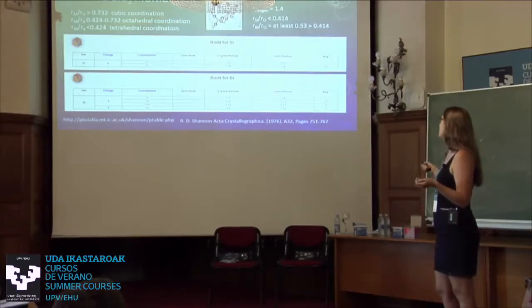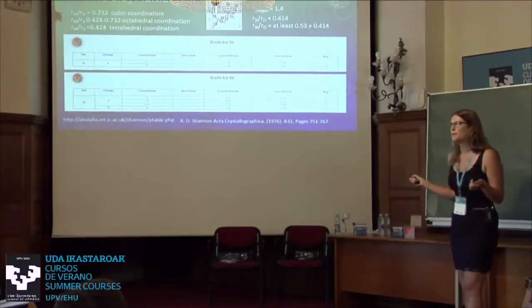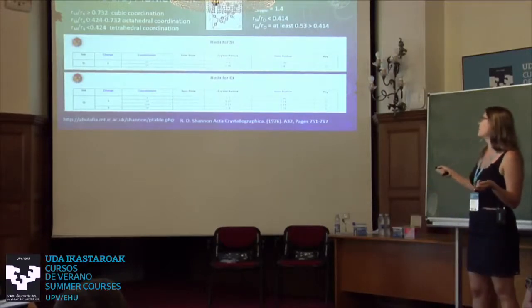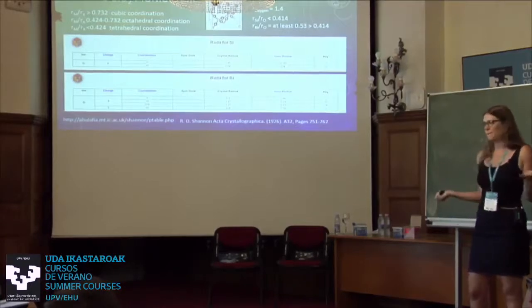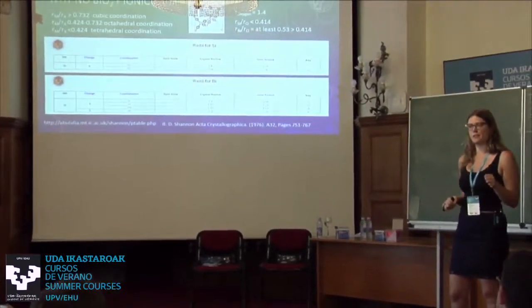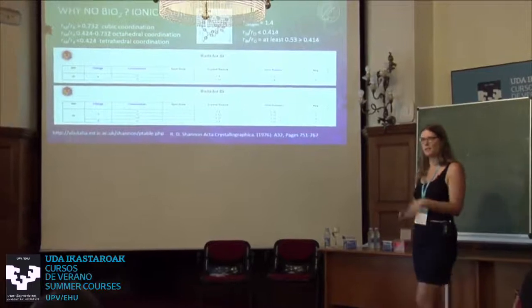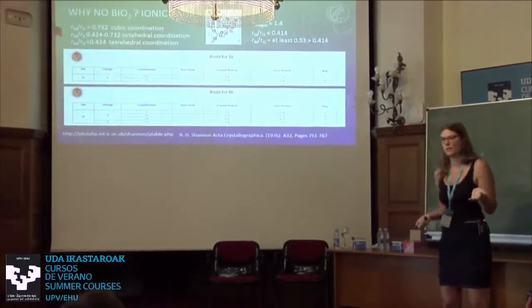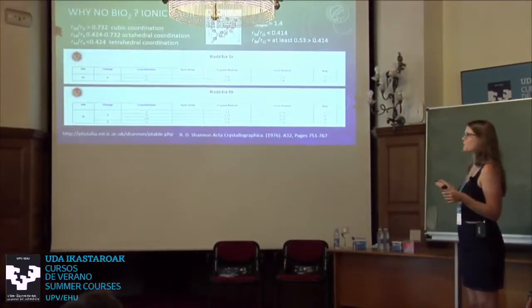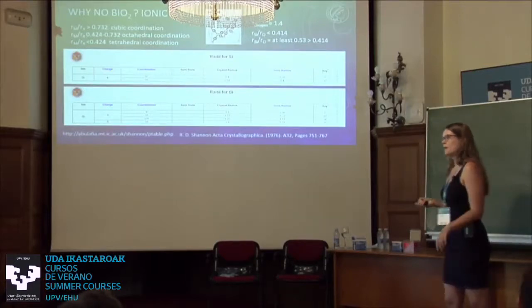And if you divide 0.76 by 1.4, you get 0.53, and this is larger than 0.41. So there is no way bismuth will ever fit in an oxygen tetrahedra. It just doesn't fit from the size, okay? You can only have it in octahedron or anything else. So you can't just replace that here. Yeah?